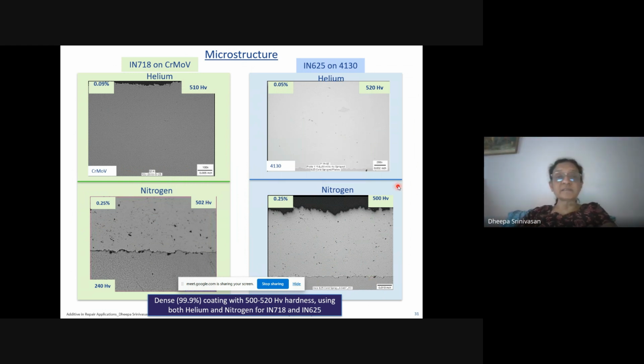So typically, this is how the microstructures look. This is the substrate and this is the coating. Likewise, this is the substrate and this is the coating. I think in the top picture, you can't really see the substrate. So we are trying two different nickel-based alloys for better functional properties, such as better corrosion response and better wear resistance, onto chromoly steel.